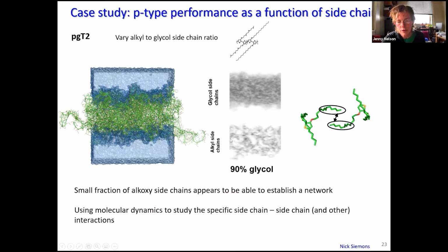This is the image of the structures formed by alkyl side chains when you have just 10% of alkyl and 90% of glycol chains in the polymer. And it appears that these chains are able to form some kind of connected, or if you like, percolating structure. Whereas if you ask the same question with 10% of glycol side chains in alkyl, you don't see the same degree of interconnection. And we believe this is due to the way in which the alkyl side chains like to interact in the presence of a strongly polar environment. So this is work in progress. We hope to gain some more insight into the mechanism.